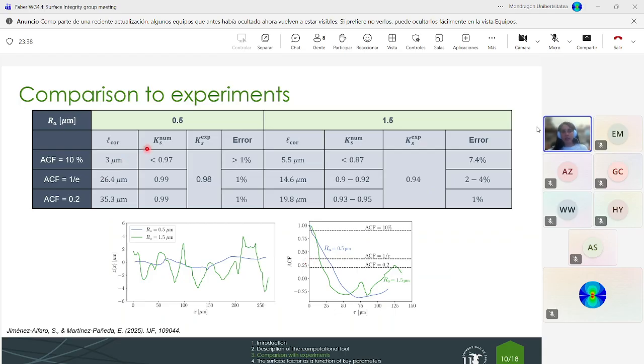This is the surface factor obtained numerically, and this is the surface factor obtained experimentally. So as you can see, the one that gives the best result is the ACF equal to 0.2, where the error between the experimental results and the numerical results is less than 1%. This is very interesting because this criterion, ACF equal to 0.2, is the criterion used and proposed by the regulation. So it is also the one that gives the best results for us in our computational framework.